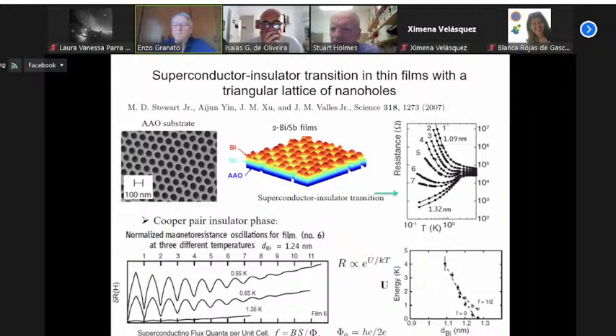But I think there are situations for the superconductor-insulator transition in which the insulating phase is a localized insulator, and for that you actually find this hopping conductivity. But those are different from this system here and the phase transition that I'm describing between superconductor and insulator. So there's a Mott insulator.